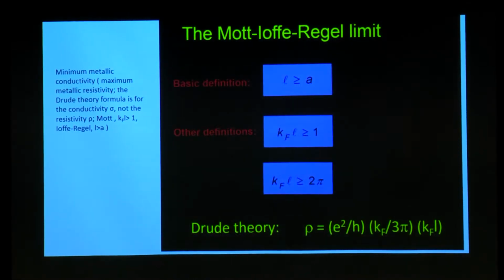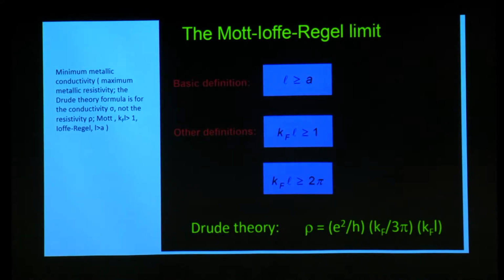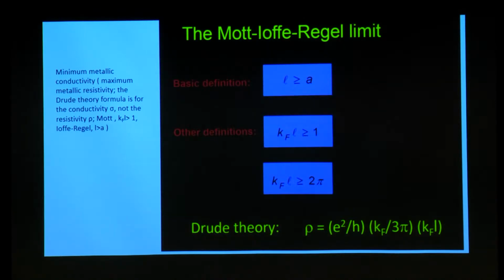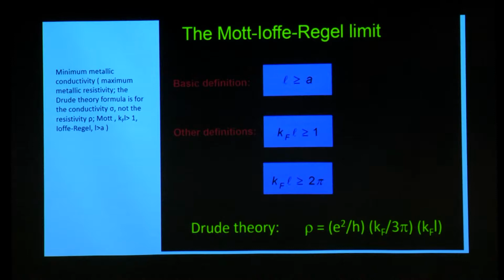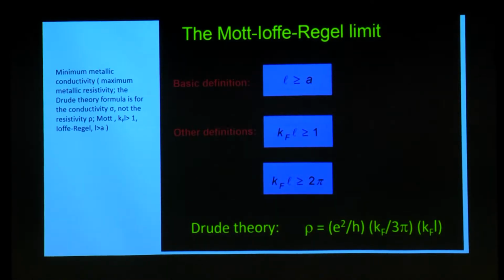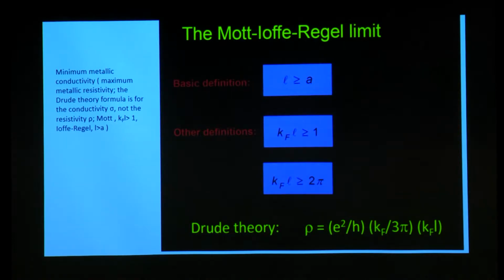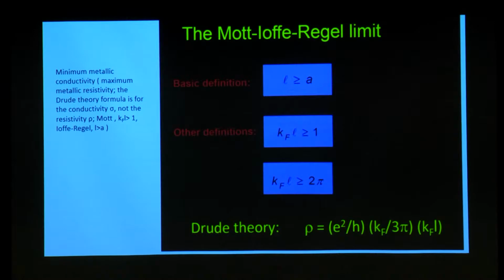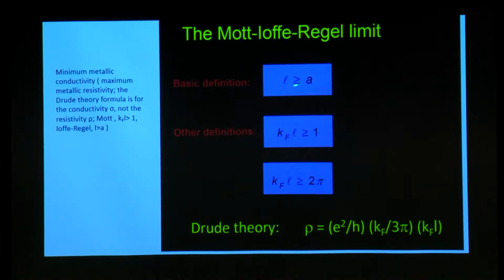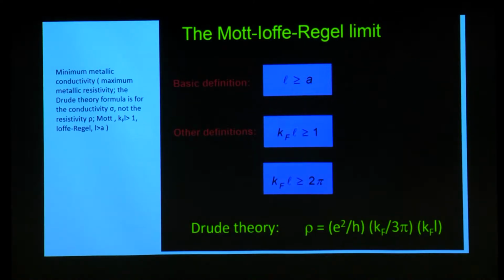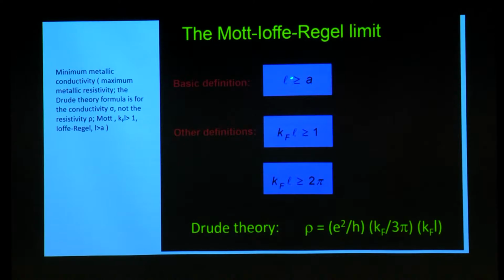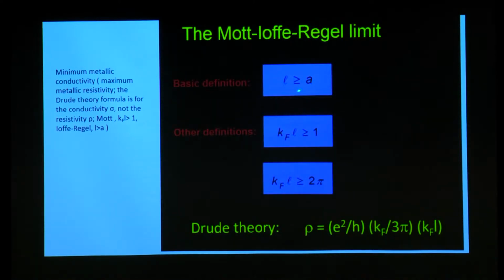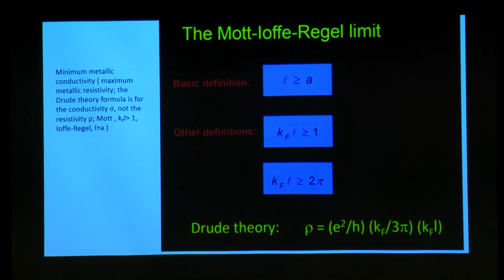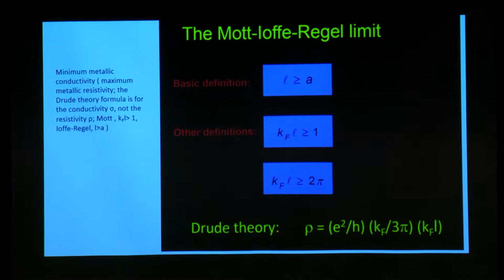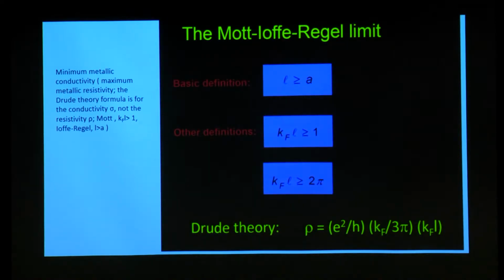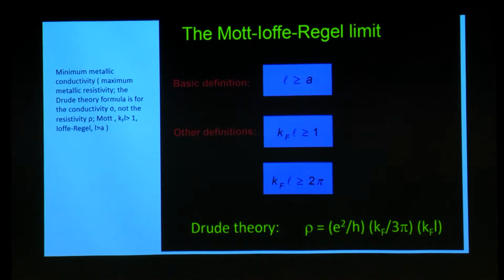Then there is the other thing which I would like to introduce, which is what is called the Mott-Ioffe-Regel limit. This comes about simply because electrons are waves. So if electrons are waves being scattered by somebody, then that somebody better be near at hand. In the case of electrons in metals, the minimum distance between scatterers is expected to be the lattice constant in crystalline metals. So if the mean free path for electron collisions is of the order of the lattice spacing, then the electron is as scattered as it can be. And that sets a limit for the lowest possible conductivity of the system.